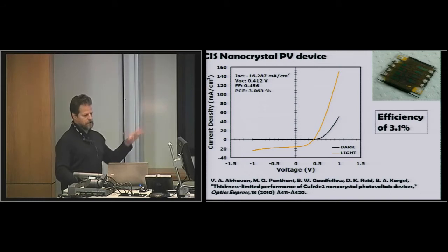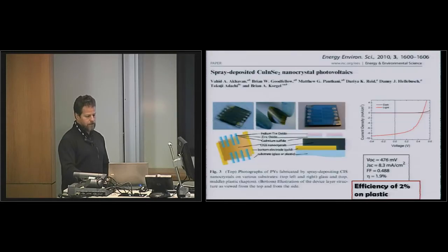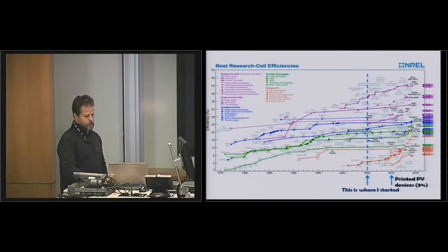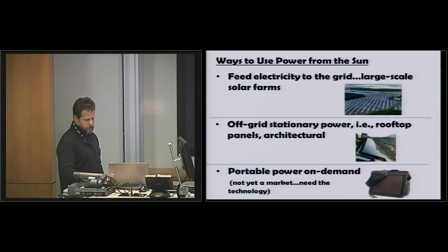But back in 2009 or so, we were getting just spray painting, just about 3% efficiency at that time. And we could do that on plastic. So it's not really commercially viable, 3%, but at the time that was the record for a nanocrystal device. So back in 2010, now on the roadmap, they added sort of printed quantum dot cells. And so there was a study on lead sulfide quantum dots from NREL, from Art Nozik's group, where they were at about 3%. So that's their point. That's about where we were at that time with this material.